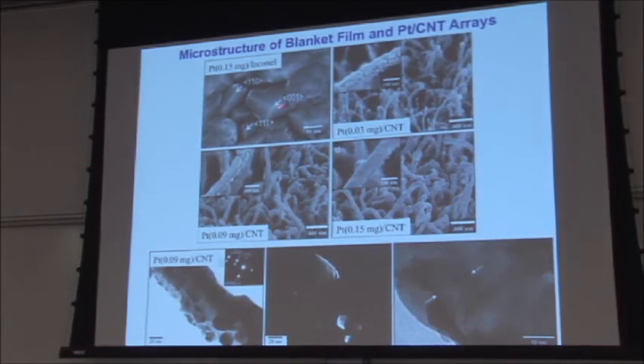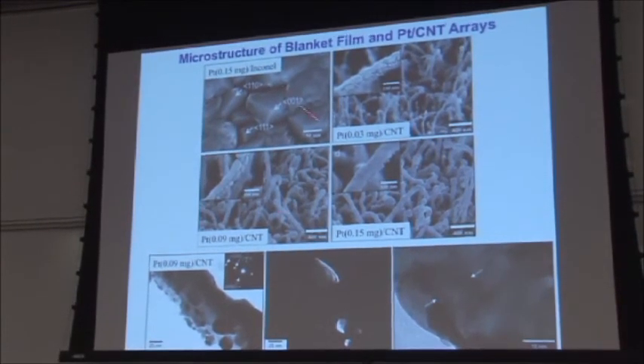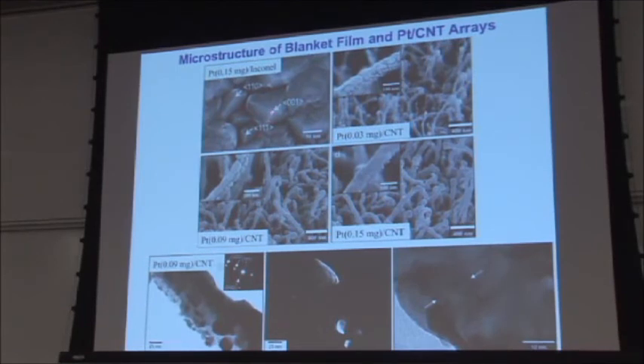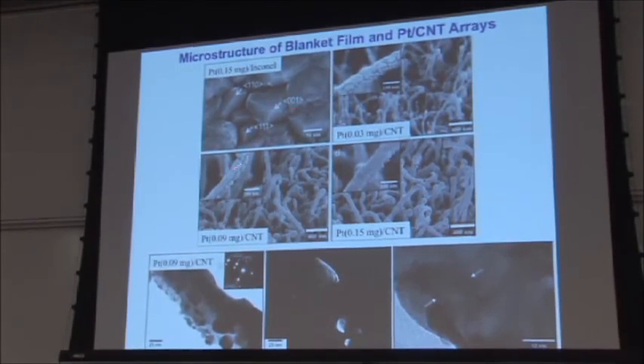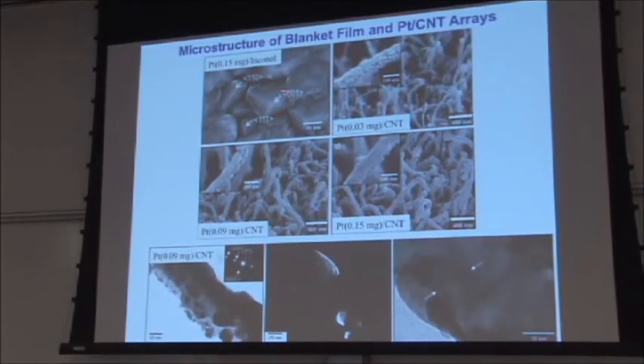But as far as we're concerned, we had this very, very coarse baseline structure of coarse platinum crystallites in the 001, the 111, and the 110 orientation. You can tell by the symmetry. So you have 4 111 planes here terminating at the surface.